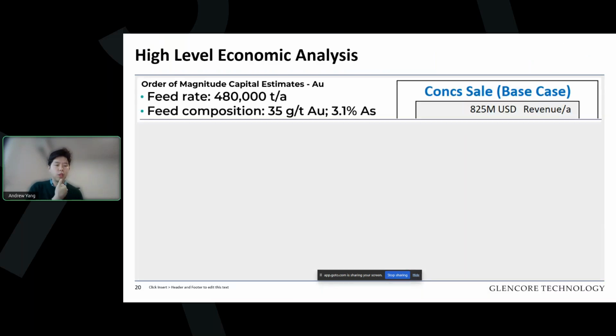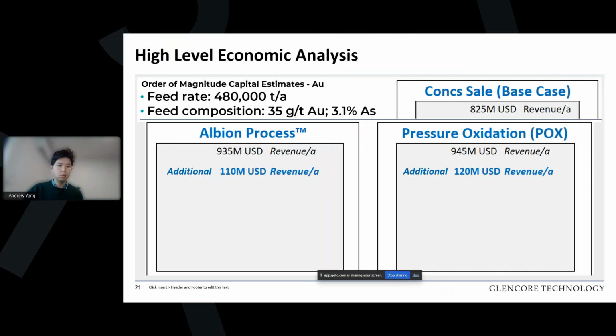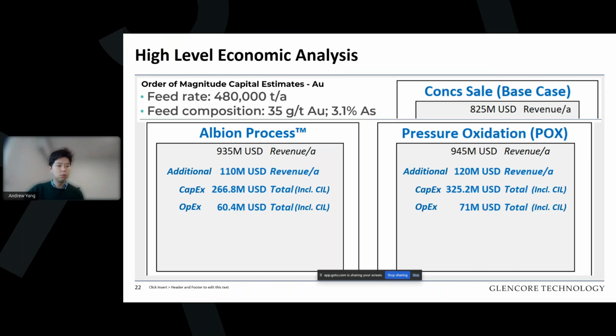Okay. So this is our base case, and we can see that using these assumptions, our base case has that amount of revenue per year, 825 million USD. If we then decide we're going to produce metal in country and on site, we're going to have additional revenue. We can see for the Albion process, an additional 110, and with the higher recovery, POX will give you an additional 120. These are the nominal CAPEX and OPEX, including the CIL.